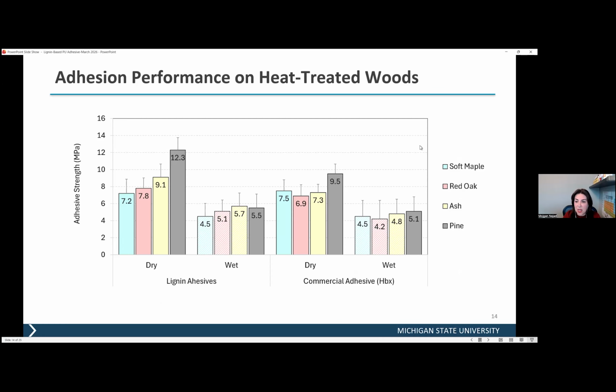We had different samples of heat-treated soft maple, red oak, ash, and pine that were provided to us. And we tested our lignin-based adhesive versus a commercial Henkel adhesive. What we found is that our adhesive, again without optimization, has better performance, better adhesion strength on heat-treated wood compared to the commercial adhesive. Sorry, and there's a typo here. I didn't notice. My apology.